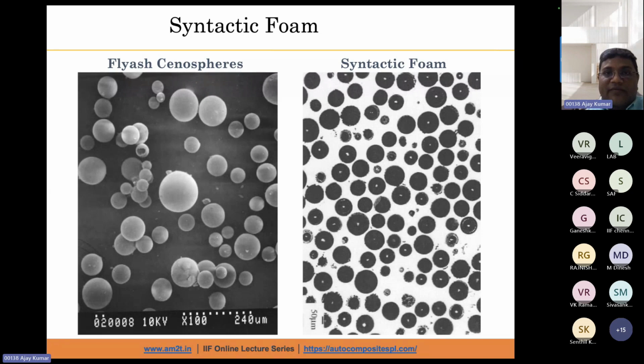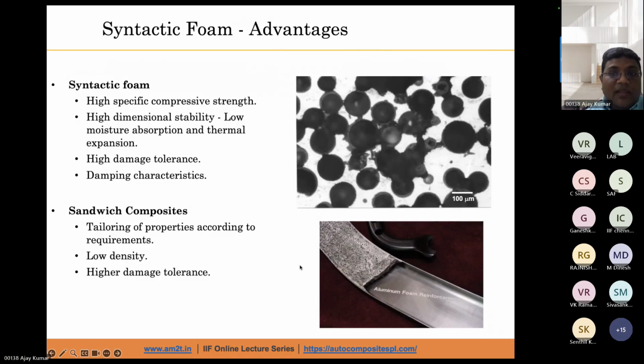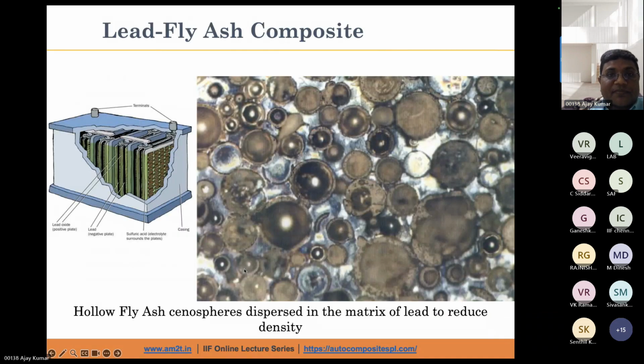Now we can also make the syntactic foams. So as I mentioned that pressure infiltration, we can use the fly ash cenospheres as a reinforcement. A lot of work has been reported in this area, even from India also. Some of the labs like CSIR Trivandrum lab, CSIR AMPRI, and other IITs also, they have reported this type of work. They have used the fly ash as a cenosphere as a reinforcement material, and they have made the syntactic foams for various applications. They are lightweight and they have very good damping properties. And this is the example of lead fly ash composite. So they have used the hollow fly ash cenospheres. They can disperse in the matrix of lead.